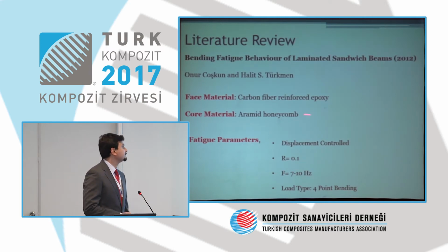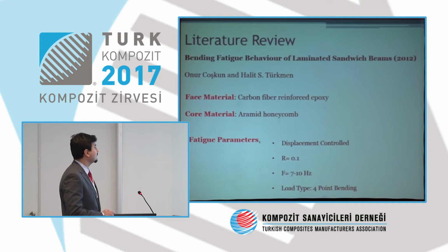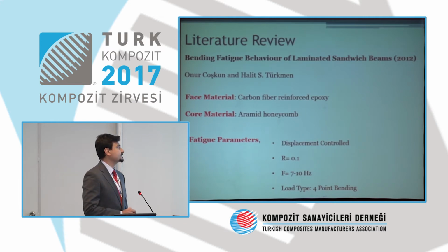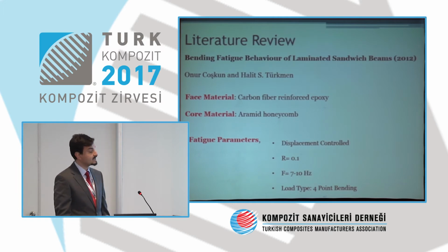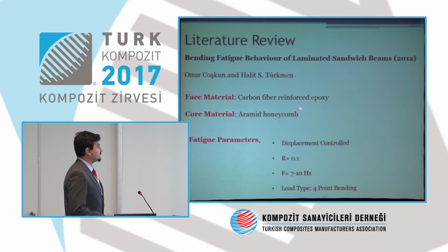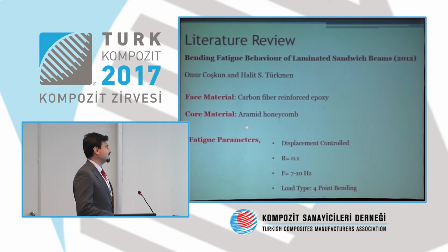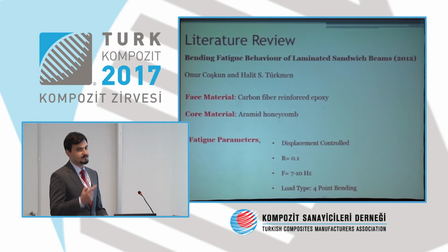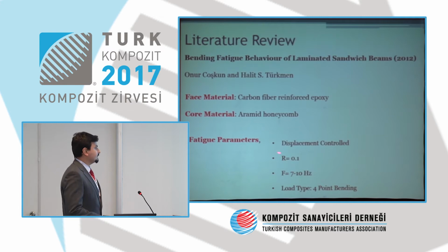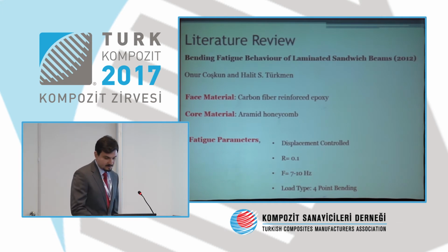This is the second paper by Onur Coşkun and Halit Türkmen. Bending fatigue behavior of laminated sandwich beams was published in 2012 in Advanced Materials Research. They use the same face material, carbon fiber reinforced epoxy, and a meta-aramid honeycomb core. It's similar to the previous one. Their fatigue parameters: they do their tests displacement controlled. R, the stress ratio, is 0.1, and their frequencies are 7 and 10 hertz. Load type is 4-point bending, and